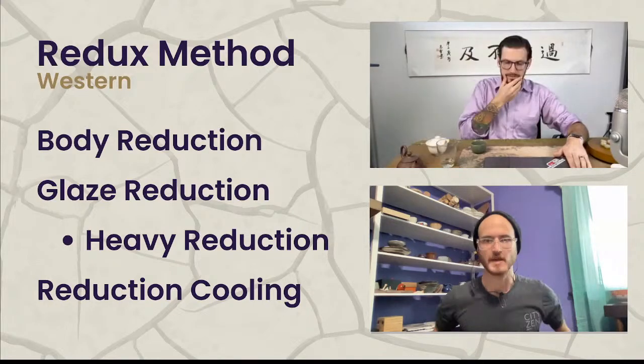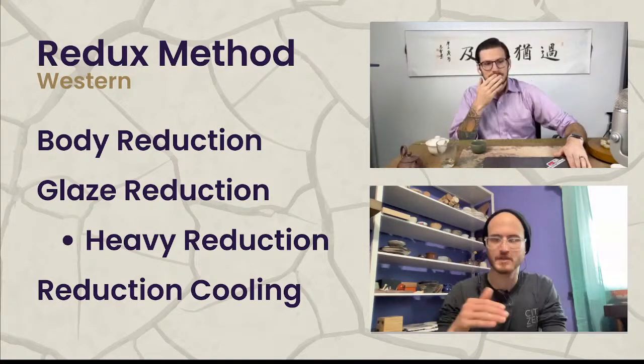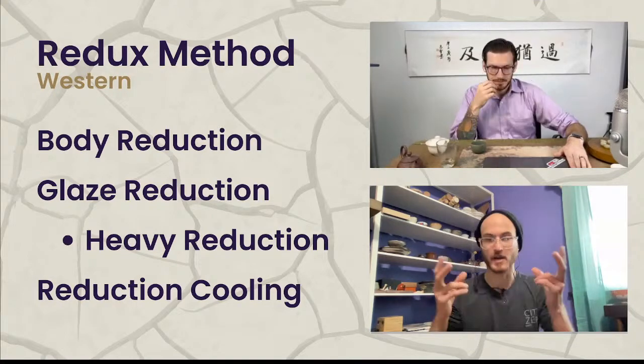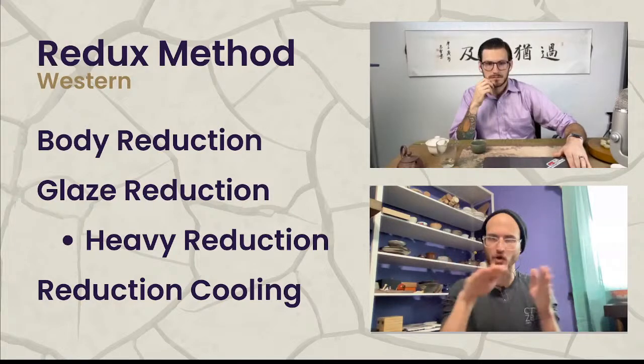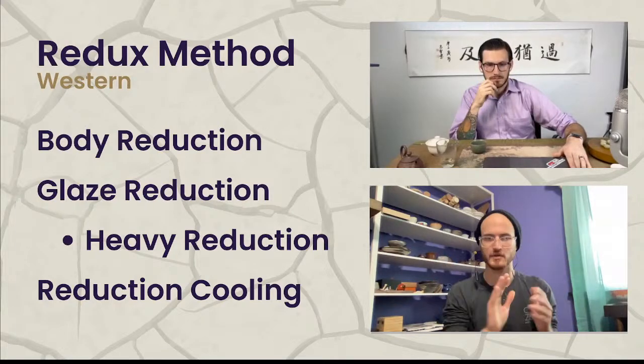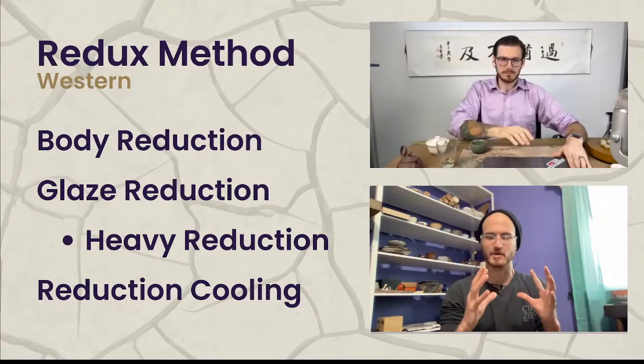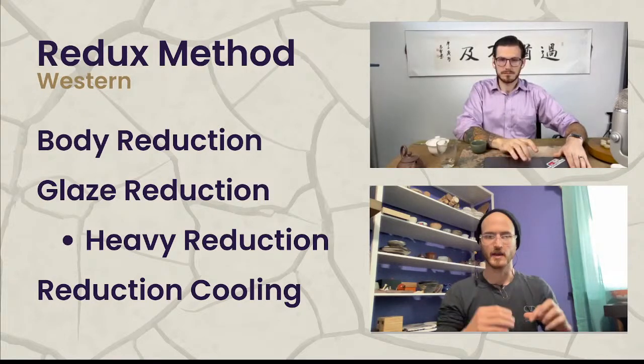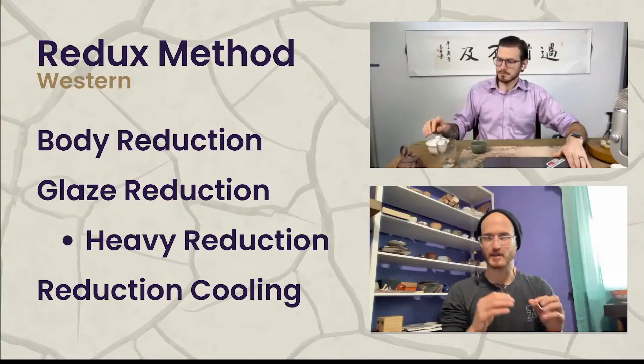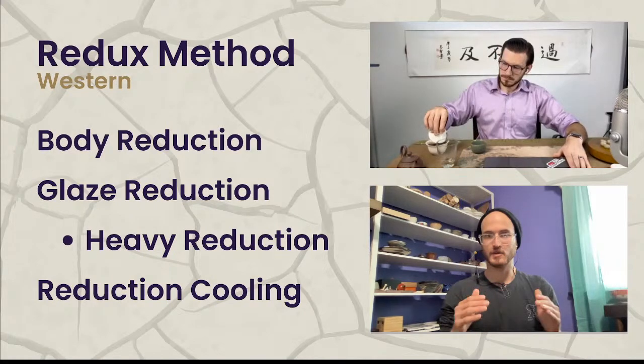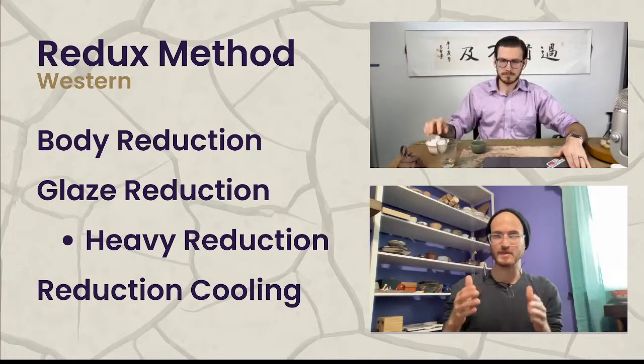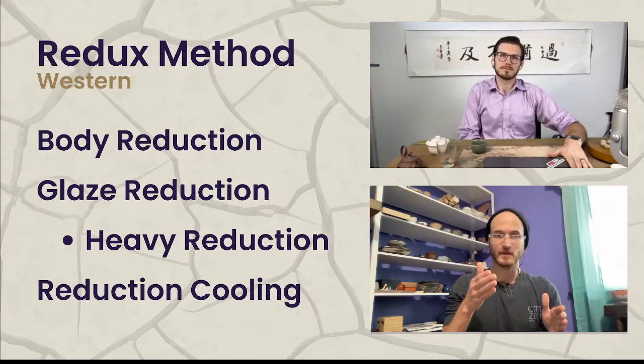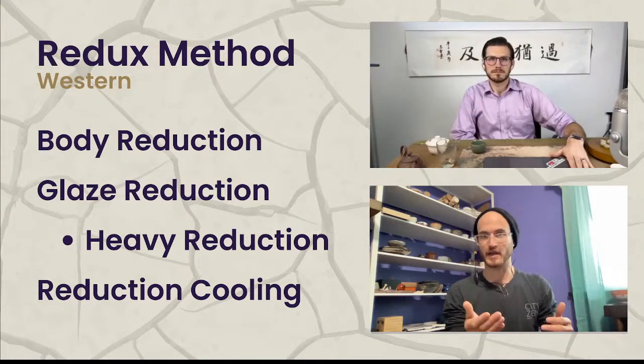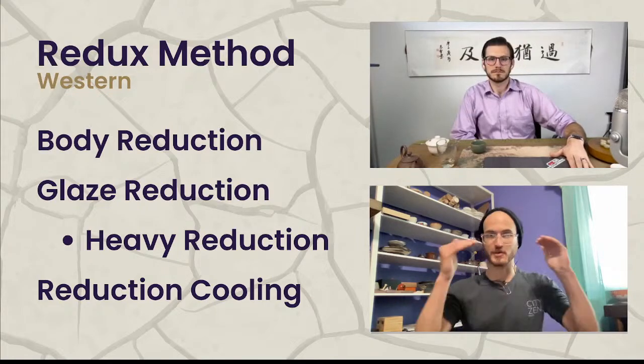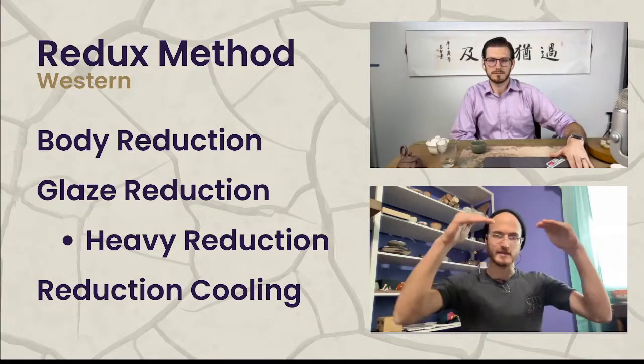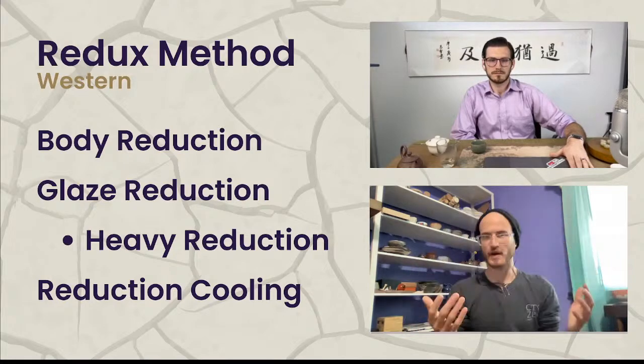Yeah. So basically, you have natural cooling, which means that you're just what I call clamming up the kiln. You close all of the ports that go into the kiln, and make sure that it's as sealed as possible, so you can get a slow cooling as best as possible. Right. So that's a natural cool, and then you can do a crash cool, which basically means that you're leaving the kiln open, and that could be with flame or without flame, in order to get the temperature to drop from its peak down to a lower point, whatever that may be, right?